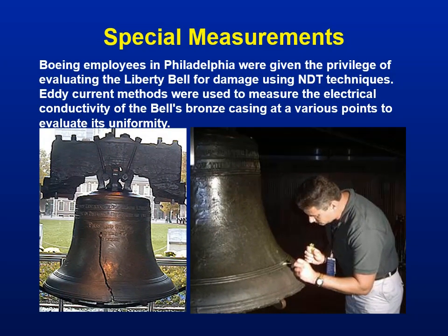Special measurements. Boeing employees in Philadelphia were given the privilege of evaluating the Liberty Bell for damage using NDT techniques. Eddy current methods were used to measure the electrical conductivity of the bell's bronze casing at various points to evaluate its uniformity.